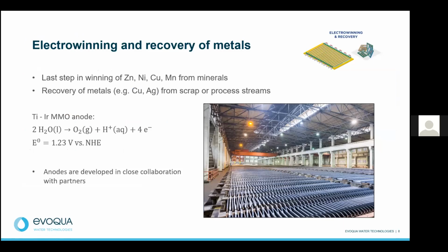Another application that's slightly related to this is metal winning, which is where the metal of interest is electrodeposited in rather bulky films on the cathode after it has been extracted from either mineral ores or scraps, where the goal is to isolate this metal from the mixture in a very pure way and then process it further or sell it. Again, the desired counter reaction here is oxygen evolution, which, considering the usually quite acidic conditions of this process, means that you will need iridium.